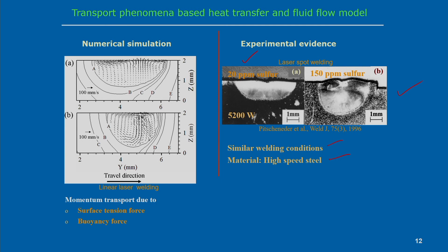Numerical simulation shows that velocity vectors plotted at each node point reveal completely different flow patterns in these two cases — one case shows flow in one direction, the other shows the opposite direction. We can predict the effect of surface active elements by carefully modeling the surface tension force, specifically the temperature coefficient of surface tension. In laser welding, the driving forces for material flow are the surface tension force and buoyancy force only, since electromagnetic force is not considered.